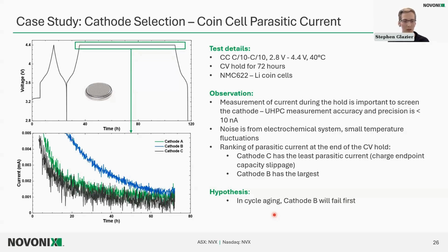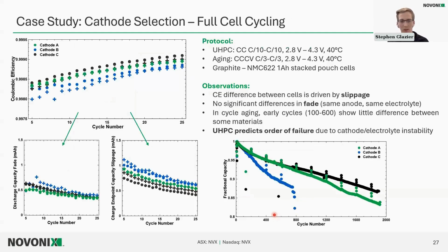So then after about a week of coating and building cells, getting cells onto formation, and then into UHPC testing and sticking cells on for long-term cycle aging, in our UHPC testing up here, we can see just in 10 or 15 cycles that our coulombic efficiency is much lower for cathode B, which had that higher parasitic current.